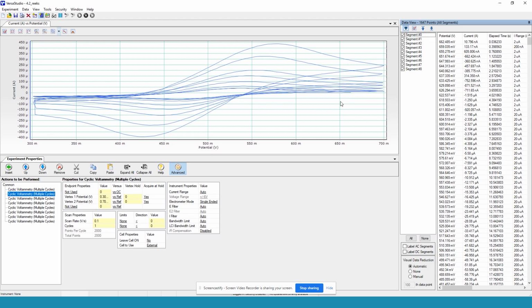Now, the main reason for this is that the solution cannot quite follow with the fast scans that we are doing. So because of this, the current increases with higher scan rates. Now, this has also something to do with the reversibility of the reaction and also with the diffusion coefficient of the species. And actually, by using the Randles-Ševčík equation, which is given in the course material, we can determine the diffusion coefficient of our active species.